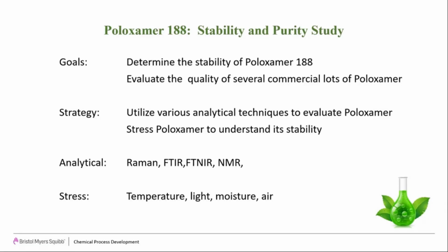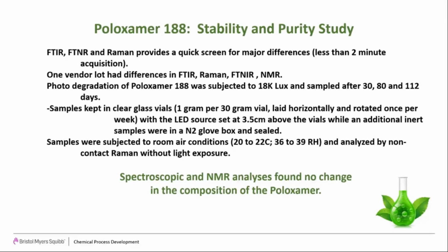An example here is Poloxamer 188. This is a stability and purity study. We used a number of tools listed here. We also exposed it to different environmental conditions. The question came up from our colleagues in the biopharma area that they had a lot that they had trouble with. So we went through the protocol of exposing it to light, different air temperatures, different conditions, and we found really no change in the Poloxamer, in this case, Poloxamer 188. It seemed to be very stable under our conditions of stress.